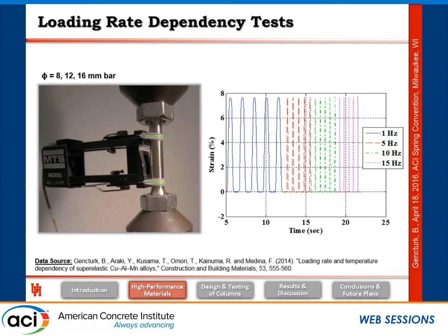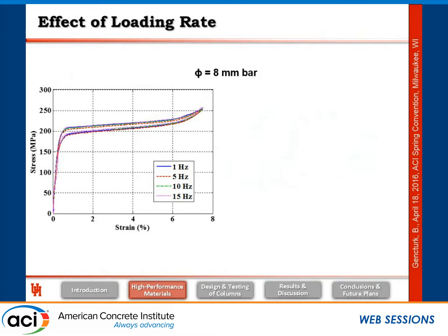There are more in this paper if you're interested, if you can go back and look at it. What we have done here is we subjected these bars with different diameters to increasing strain rates. These are cyclic loading in tension, and these are the corresponding strain rates to these loading frequencies. So earthquakes are somewhere here, and this is really getting into the shock loading rates. If you look at the response of the material, this is again superelastic, and the loops are quite stable and go up to 7% strain without any problems.